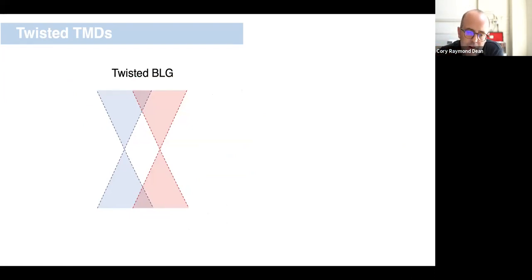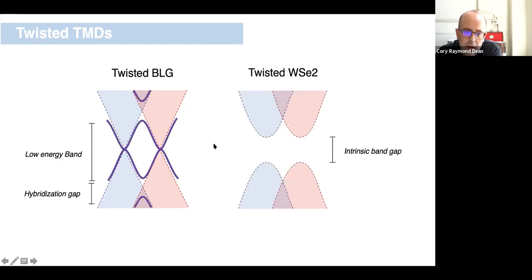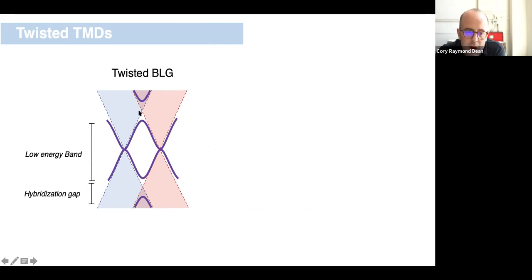So in twisted bilayer graphene, the picture that we have is that if the two layers are rotated in real space, in K space that results in a shifting of the Dirac cones, separated in K-space. And what happens in this system is that these two layers will basically hybridize at the point where these displaced cones cross. And that gives rise to basically a gap in the spectrum here. Okay, so you get this hybridization gap. And what that does is it results in basically the formation of this low energy band.